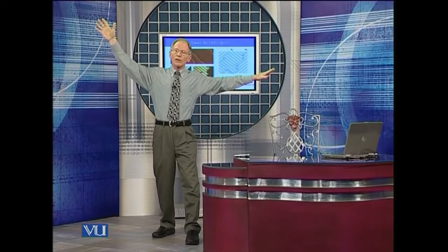Well, that's easily understood now, of course, by saying that if I were a silicon atom, I would have 2 back bonds and 2 dangling bonds. And if you create the clean surface, I want to get rid of these dangling bonds. I want to move a little bit and form a bond with my partner who looks just like me, like that. Now I have a dangling bond, only 1. That's what these lozenge-like things look like in the current image.